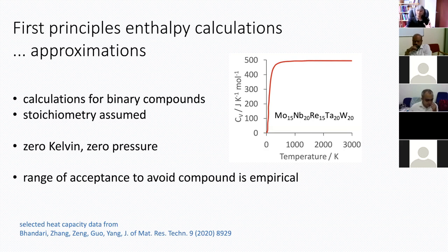Now, why am I mentioning heat capacity here, whereas we are talking about first principles calculations? Why does the heat capacity change, and how does that affect the enthalpy? Well, enthalpy changes can be calculated as a function of temperature by integrating the heat capacity versus the temperature. It's classical thermodynamics. So if you calculate an enthalpy term for zero Kelvin, it doesn't mean that it applies at a higher temperature. And I demonstrated this in the case of cementite. If you do a first principles calculation for enthalpy at zero Kelvin, zero pressure, it obviously is not the same as a measured value at a high temperature. Okay.